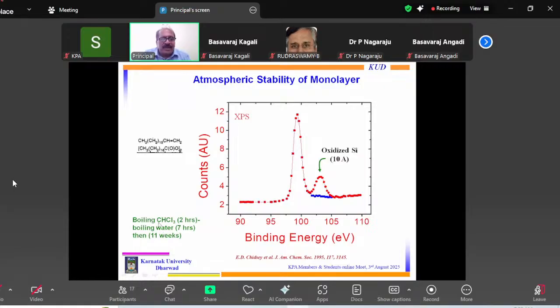Not only that, very interestingly, they took such interfaces. They boiled them in CHCl3 for 2 hours, boiled in water for 7 hours, then left them in open condition for 11 weeks, months together. They do not see any oxidation. That is the stability of these monolayers.